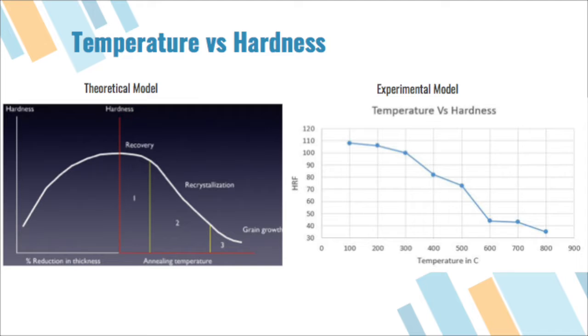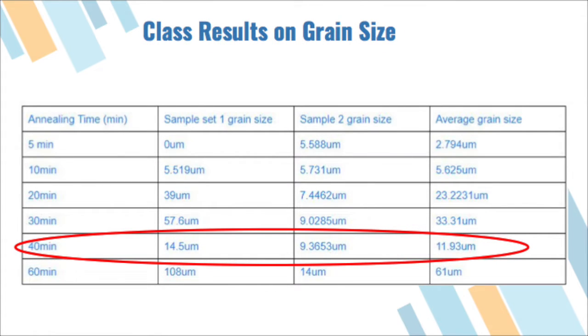In the procedure, we decided to choose 450 degrees Celsius as the annealing temperature with varying time, and as you can see, this falls in the middle of the recrystallization process. We hope to achieve a better understanding of how time affects the micrographs and grain size. So this is the data obtained for the grain size, utilizing the magnification and counting grains along randomly selected lines in order to follow the ASTM standard formula.